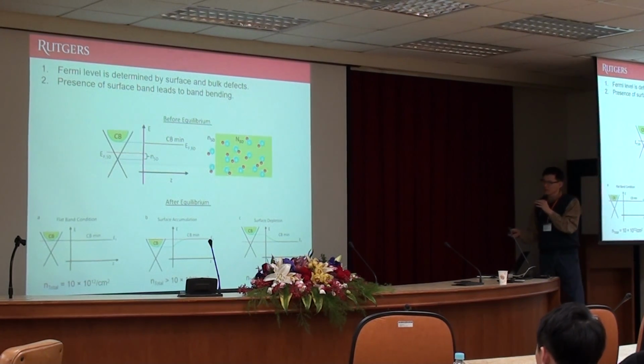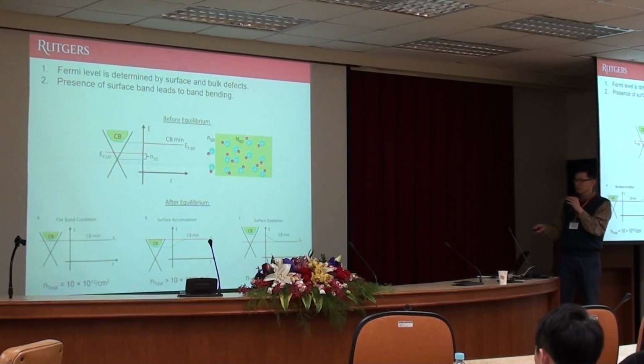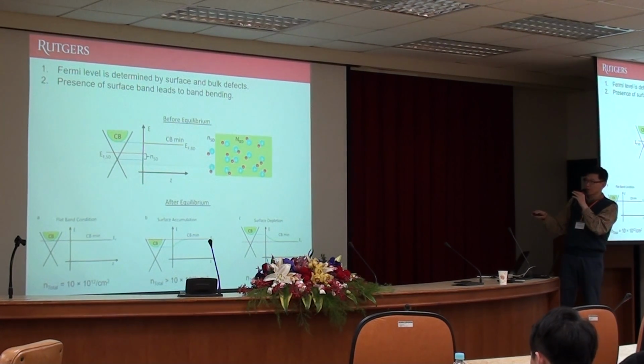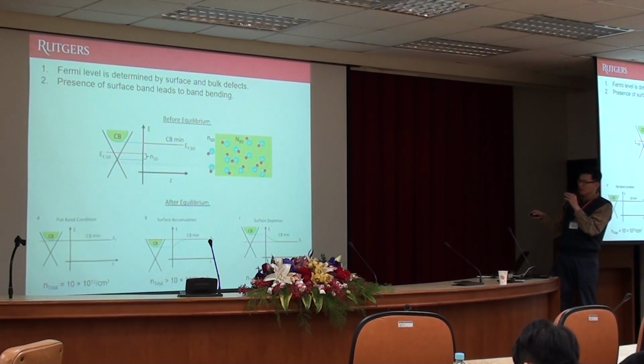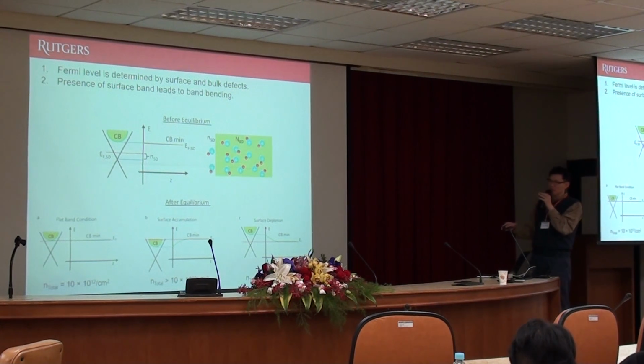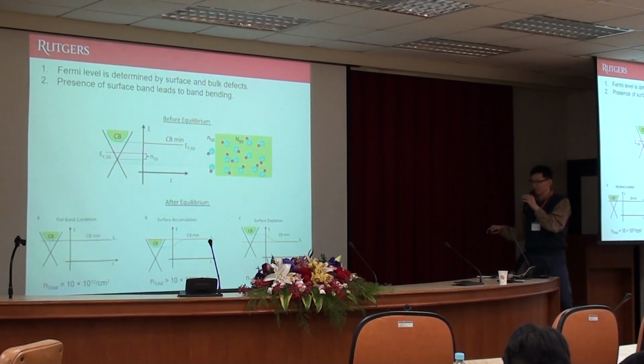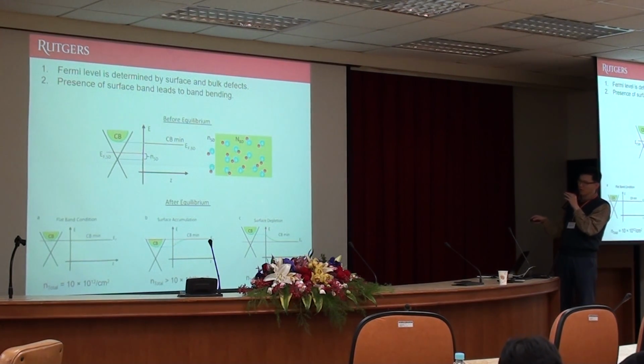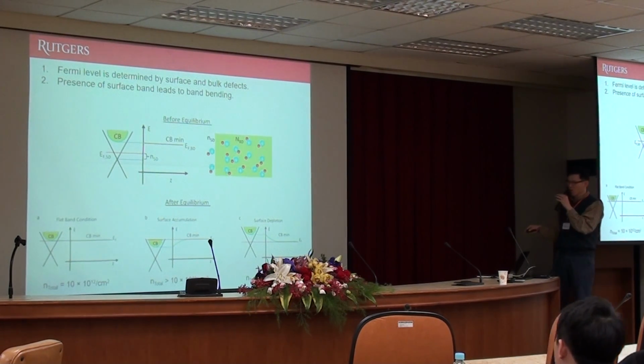Then let's take a look a little bit more at exactly how we achieve downward or upward band bending. So if you check, there's a surface band, and you know roughly where the bulk band is, and all these levels. And then it turns out that if your total sheet carrier density is exactly 10 to the 13 per square centimeter, then the bottom of the conduction band matches and is flat. You actually have a flat band. But if your total sheet carrier density is higher than this value, 10 to the 13, then you have an accumulation layer. If your total carrier density is lower than this value, you get the downward bending. So this is what we want. We want carrier density lower than 10 to the 13. That's the criteria.